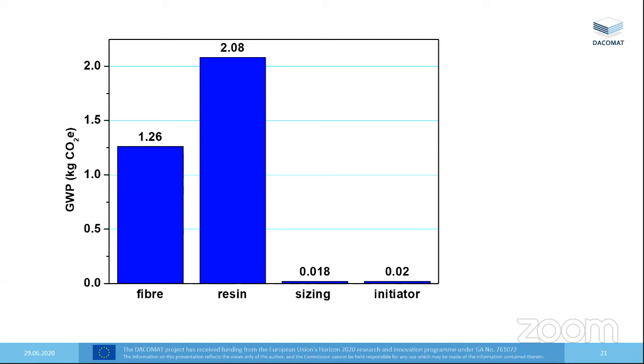We rather suspected that this is what we would find. The sizing agent and the initiator are of no consequence. They do have an impact, but it's a very small impact. And actually, if I was to put error bars on these plots, you'd find that the sizing agent and initiator fall within the errors that we have within these kinds of analyses anyway. So we can effectively ignore those. If they were then to choose something outside of that range that we've looked at, we might have to revisit it, but I would still be very surprised if they turned out to be of any importance.